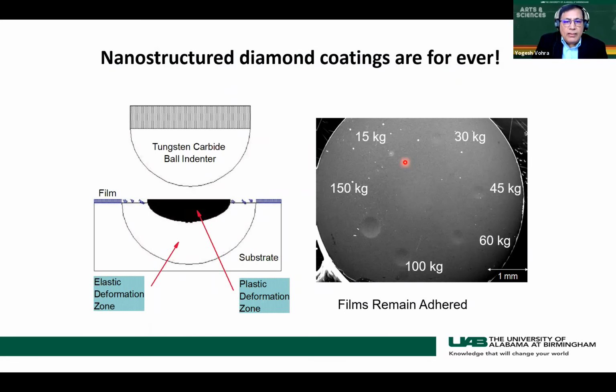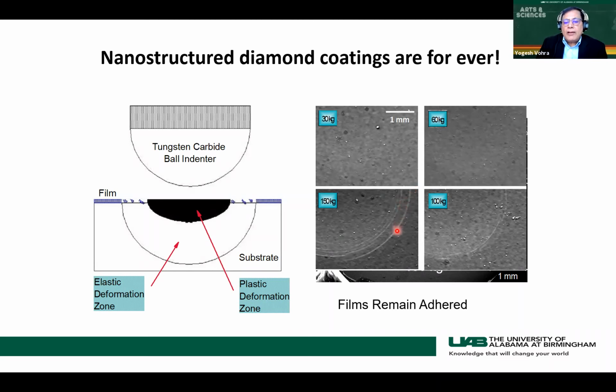Another surprising thing really was, to use that phrase, that diamond is forever. Once you deposit these nanostructured diamond coatings on titanium alloy, what we found was that they are very difficult to remove. So if you try to push indenters into very, very high load, the film still is adhered and only shows some micro cracking at the periphery, which was an interesting observation, because diamond initially was thought to be an intrinsically brittle material, which will shatter. But these nano indentation tests, especially on the nanostructured diamond coatings on metals, have indicated that these are really films which are not susceptible to delamination.